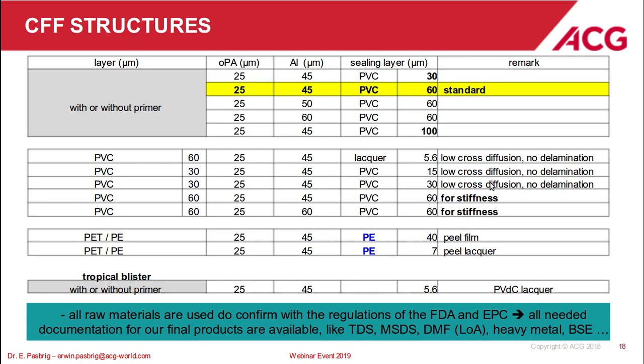Here you see the structures we are producing. On top, you see all of the three-layer structures with and without primer. The yellow bar is the standard laminate. As you know, this is 25 OPA, 45 aluminum, and 60 micrometer PVC. The first row is with 30 micrometer PVC as a sealing layer. This came into the market for the second generation of Spiriva.